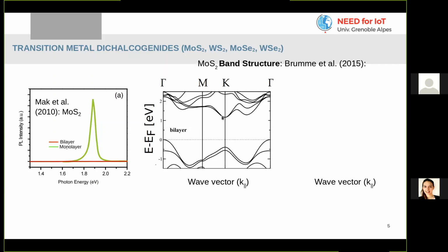So there are positions for energy and the wave vector at which an electron is allowed to exist. Now in a bilayer system, we can make it so that an electron occupies this band, for instance. And now electrons will want to lower their energy at some point, so it could possibly travel over here to a lower energy. However, it cannot do that by emitting a photon, because there's a rule that says, if an electron wants to emit energy by emitting a photon, it has to do so by not changing its wave vector. So here the wave vector is obviously changed by going from one band to the other, so it cannot emit a photon doing that.